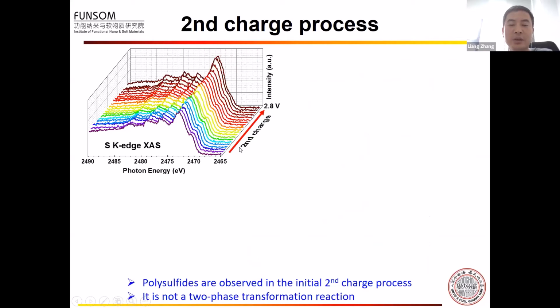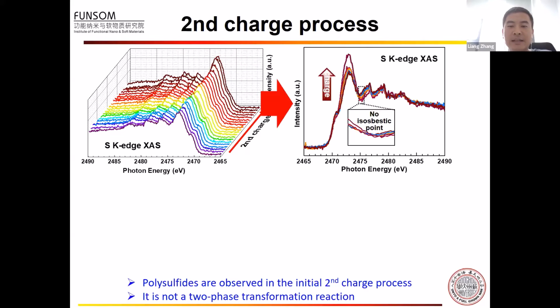We also use the same method to record the sulfur K-edge for the second charge process. We can see the intensity of the main feature also increases, but the intriguing thing is that we can find the lithium polysulfide feature even in the very beginning spectrum. This result clearly indicates the involvement of lithium polysulfide in the second charge process. In addition, the stack plot didn't show the isosbestic point. This indicates the second charge process is not a two-phase conversion reaction.